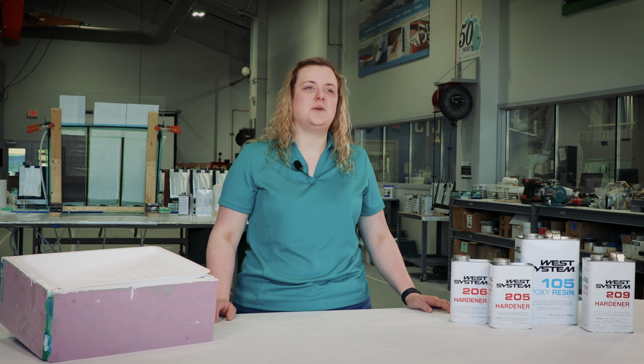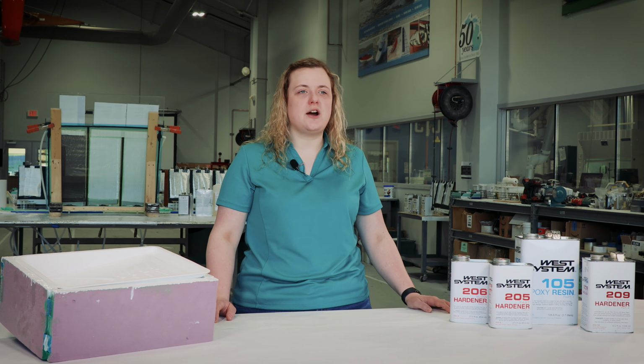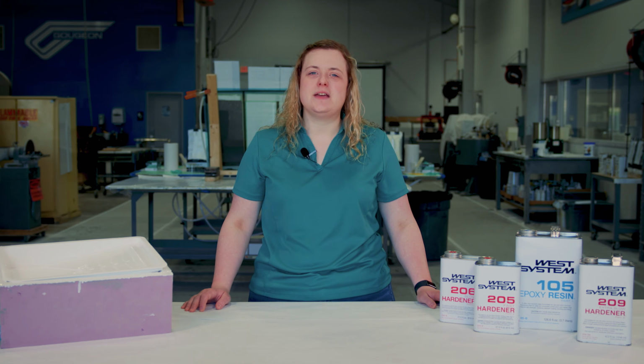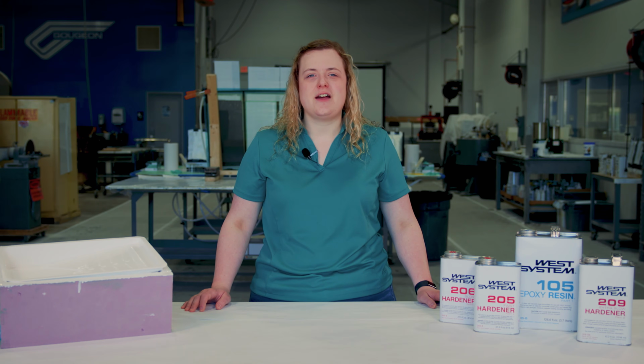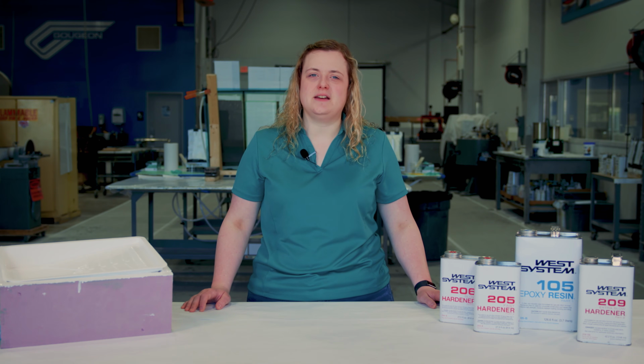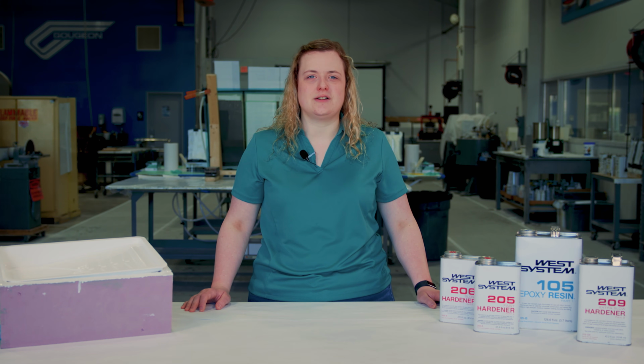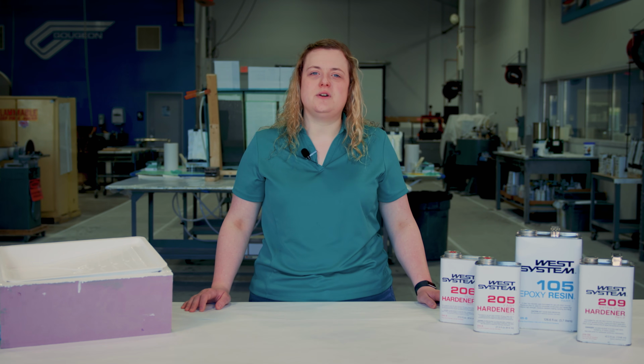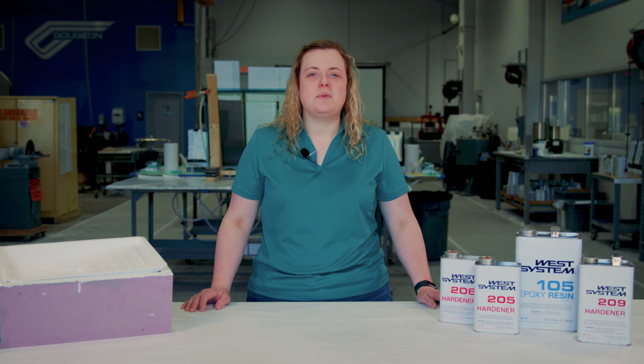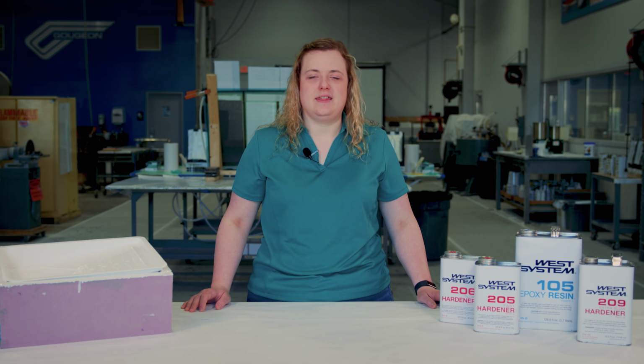Keep in mind that when working in warm temperatures, your recoat window will also be affected. We can use the general rule of thumb that for every 18 degrees Fahrenheit temperature change, we're going to affect the cure speed of the epoxy by a factor of 2. That means if we're used to using the 105 resin with the 206 slow hardener at 72 degrees in a thin film, we might be used to a 2-hour working time. But if you suddenly are working at 90 degrees Fahrenheit, it's only going to give you about 1 hour to work with it in a thin film.